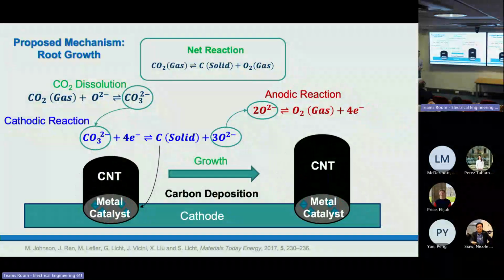So this is a different mechanism, but it is similar. It's called root growth. Instead of the metal catalyst staying on the tip of the carbon nanotubes, it facilitates the nucleation of the carbon nanotubes and stays on the substrate, which is the cathode. It stays on the surface, so the carbon nanotubes grow from the bottom, from the root of the carbon nanotubes. The net reaction and all the reactions are the same.